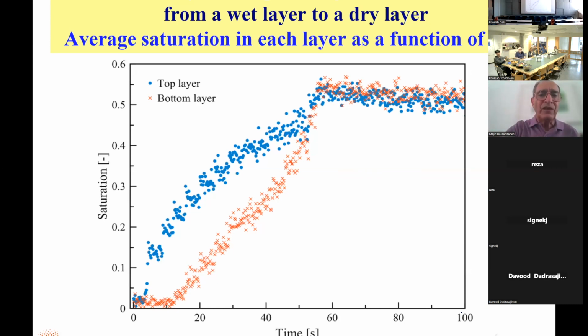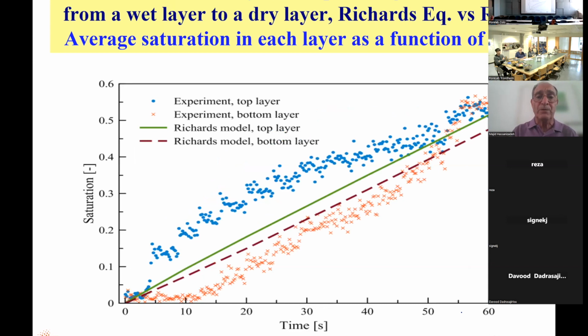Okay, so as you see, the saturation of the top layer increases as we rain water on top of it, and it reaches a plateau at some point, and then we stop raining, and the lower layer starts receiving water after some time. It takes time for it to receive water. It doesn't react immediately. It eventually reaches the same saturation as the upper layer, but it takes time, it's delayed. So can we model this with Richards' equation, for example? That has been done, and the result is the green line for the top layer and the brown dashed line for the lower layer. As you can see, they are far from the measured values.